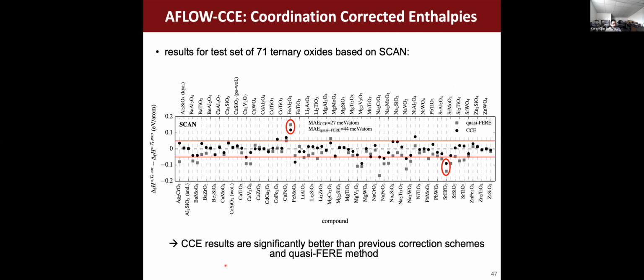So here we want to just show off some results of how this works. So you can see here that we calculate the corrections of our enthalpies of formation. So these are the CCE corrections, and we compare this to another type of correction scheme, which is called FERE, the fitted elemental reference energies, I think is what it is. But this approach basically just considers the composition. And so you can see here that if we look at the relative errors of these two approaches, you can see that the errors of CCE approach the errors we would expect from room temperature excitations. And so it does a better job of correcting the systems relative to other schemes.